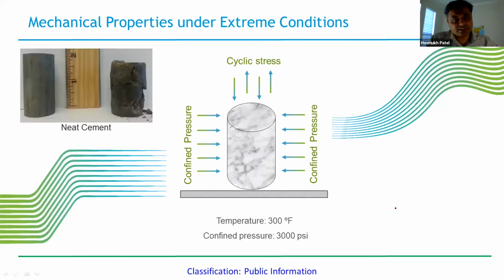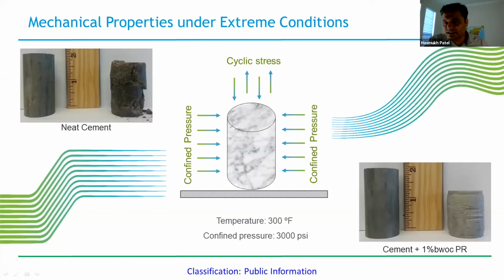So as you can see, this is the neat cement without any polyrotaxanes. When we applied the stress, what is happening? It shattered into pieces after a certain compressive stress. While in the case of one weight percent, just 1 weight percent of polyrotaxane, we were able to reduce its volume by about 30% or 27% basically, without disintegrating the cement, which is a highly brittle material, you know.